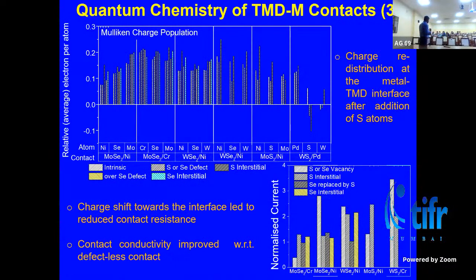And as I said, in a bulk semiconductor, when you dope with donor atoms, you create these donor states, which are active at room temperature, so the electrons are transferred to the conduction band. And when you do p-type doping, you introduce acceptor states, and these will get created at room temperature, so you have a lot of holes transferred to the valence band. The same thing we discovered that we can do in TMDs by introducing these kinds of interstitials and metal, right? So just the impurity does not help. Along with the impurity, you also need to bring the right metal into that system.